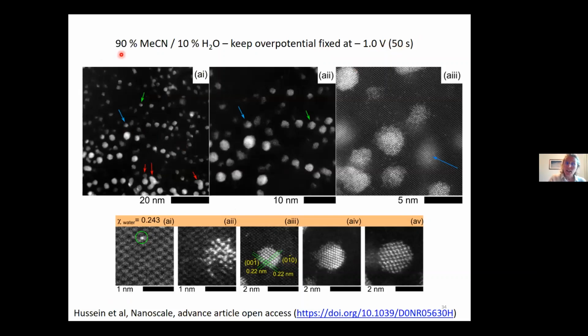This is in the acetonitrile rich solution, and what you can see, and you can see the length scales here, these are just different length scale images, is that under these conditions, you're tending to get majority crystalline nanoparticles. The blue and the green arrows just indicate the fact that we have an electron beam transparent grid that's really different to the commercial carbon ones you'll use, where you have a thin glassy carbon floated over either a copper or gold support.